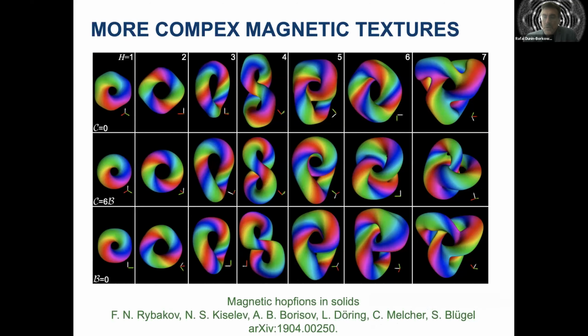And here we'd like to image them not only in 3 dimensions, but we would like to image them interacting with each other magnetically in time and in space, as well as in 3 dimensions in the presence of external optical or electrical stimuli. And so 3-dimensional imaging of magnetic states is complicated, not only because, in contrast to normal tomography, 2 tilt axes of holograms are required, but in many cases, for example, with skyrmions, you need to be able to apply an external field and cool the sample to low temperature.